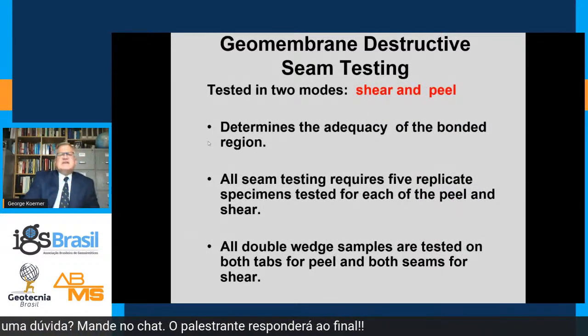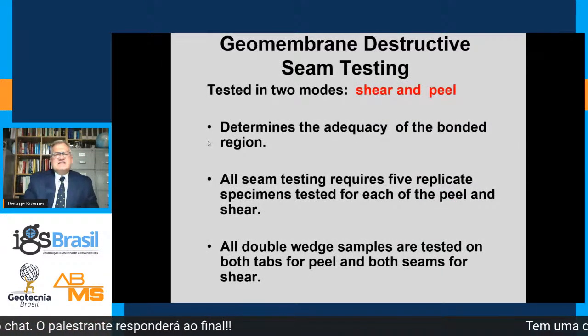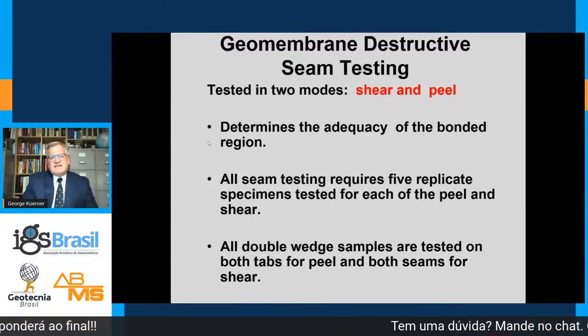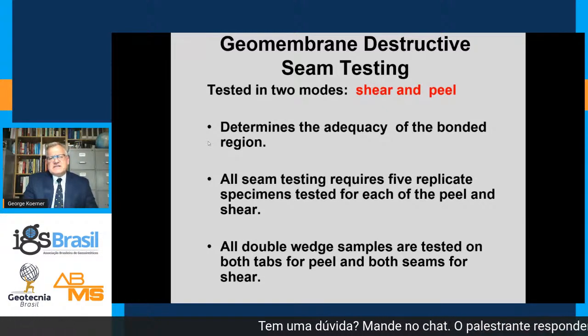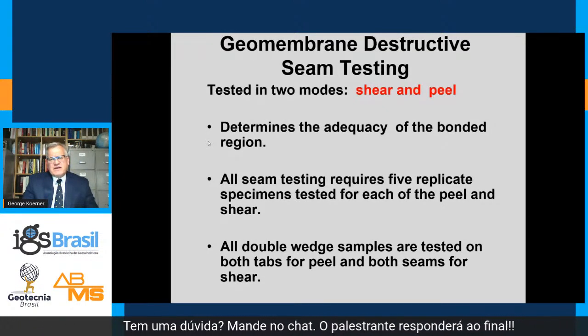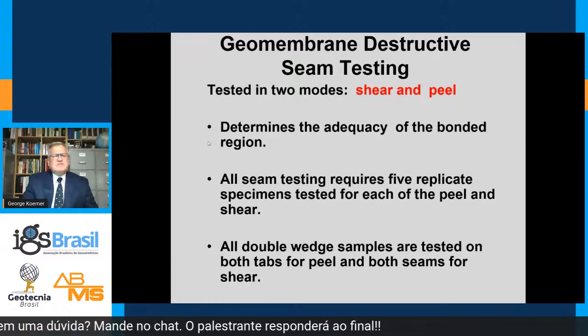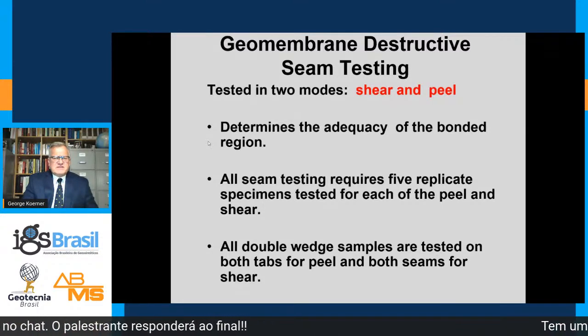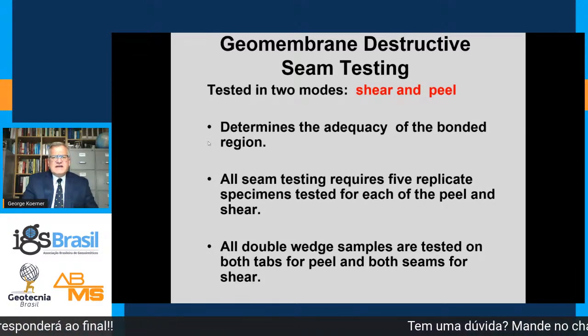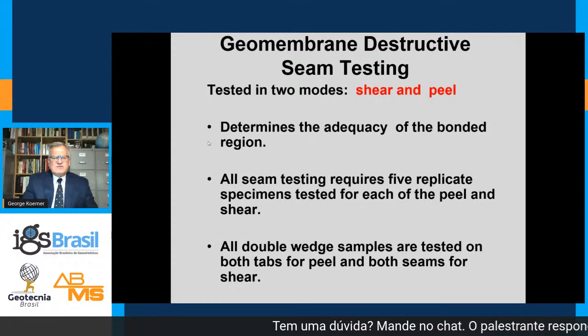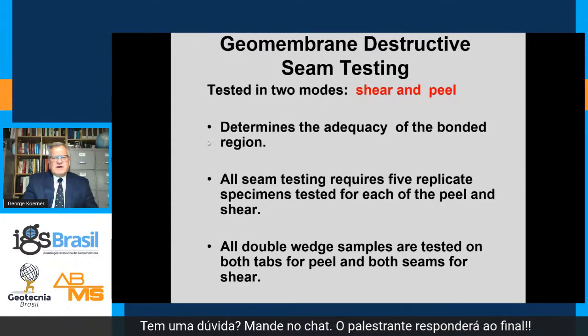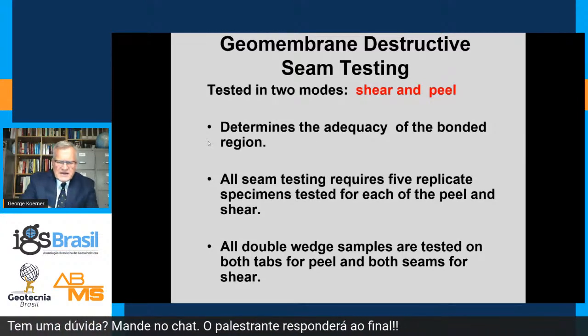As far as destructive test, these seams are not tested in the field. They're typically sent to a third-party laboratory, which is off-site. It's usually Federal Express or DHL to the site, and then tested in regards to shear and peel to determine the adequate bonding of the material.